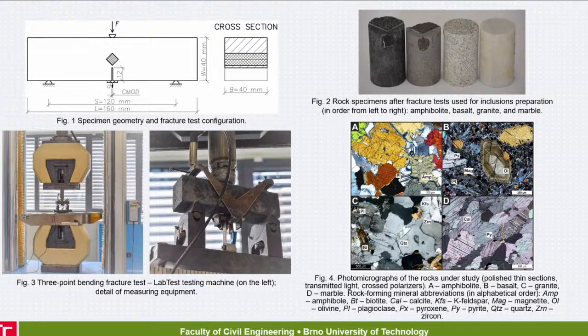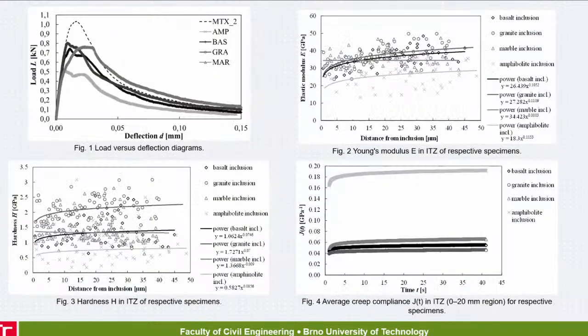These specially designed specimens were tested in 3-point bending fracture test configuration. You can see the testing machine in figure 3 on the left, and detail of measuring equipment on the right of figure 3. So the results of fracture tests, the load versus deflection, that means displacement in the midspan, were measured. As you can see in figure 1, there is a reduction in the maximal force value in the case of specimens with the inclusion in comparison to the matrix specimens or reference specimens, which were without inclusion, only matrix.